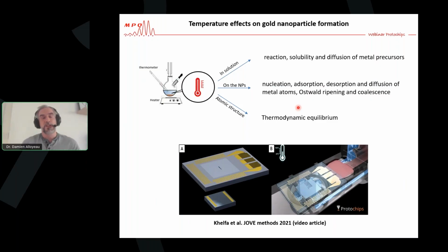And actually, just as when you work with vapor phase deposition, temperature is a very, very important parameter during the synthesis, because any atomic scale mechanism is temperature dependent. In the solution, the reaction, the solubility, and the diffusion of metal precursors depend on temperature. At the surface of the nanoparticles, the nucleation, the adsorption, desorption, and diffusion of metal atoms depend on the temperature. And even when you work on more complex systems than gold, I've shown you that for the cobalt platinum system, for example, the thermodynamic equilibrium towards which your system wants to go also depends on temperature. So if you want to understand anything about the temperature effect, you need to visualize what's going on.